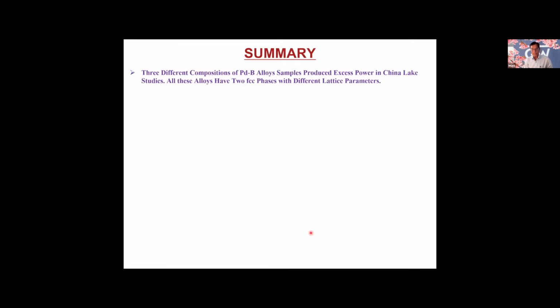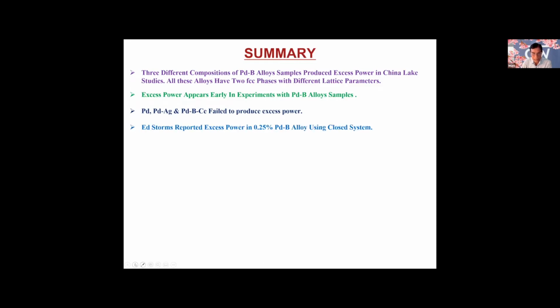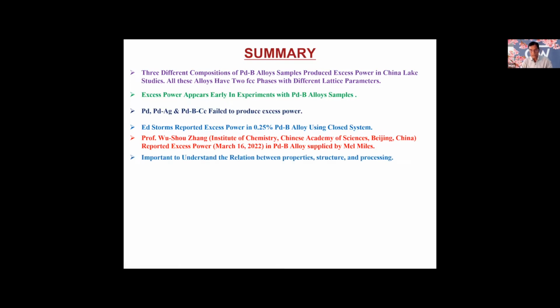So just to wrap up what we have seen so far, three different compositions of palladium boron samples produced excess power in China Lake studies. All these alloys have two FCC phases, which I mentioned before, with different lattice parameters. And excess power appears early in the experiment with the palladium boron alloys. That's another good part. And palladium silver and palladium boron cerium failed to produce any excess heat. Dr. Storms reported excess power in 0.25 palladium boron alloys using a closed system. And recently, Professor Zhang also found an excess power report in palladium boron alloy, which is supplied by Mel Miles. It is important to understand the relationship between properties, structure, and processing.